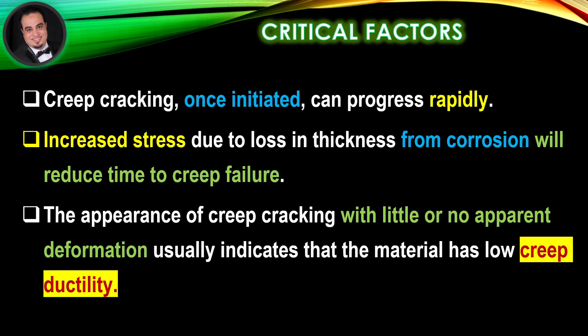Once initiated, creep cracking can progress rapidly. Increased stress due to loss in thickness from corrosion will reduce time to creep failure. The appearance of creep cracking with little or no apparent deformation usually indicates that the material has low creep ductility.